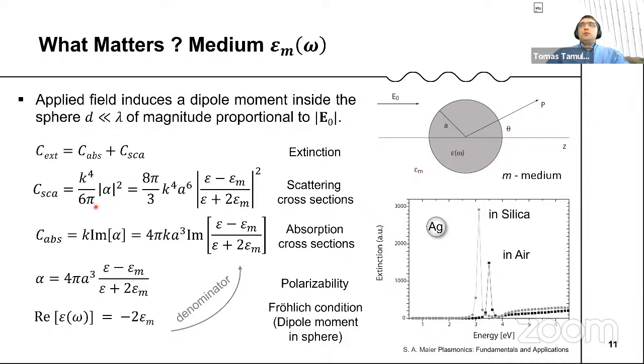I don't want to go into details with those equations, but it is important to take notice of the denominator, where we have epsilon of metal plus 2 epsilon of medium. So the medium is around the nanoparticle. And this alpha is the polarizability, which also has the same structure here. There is a condition called the Fröhlich condition that describes the dipole moment in a sphere, at which conditions it is present. And it turns out that when this denominator is equal to 0, we have a resonance. Here is an example from the same textbook I already mentioned: for a silver sphere, we have the resonance at one position, and when it is in silica, in some kind of glass, we have a position at a different energy.